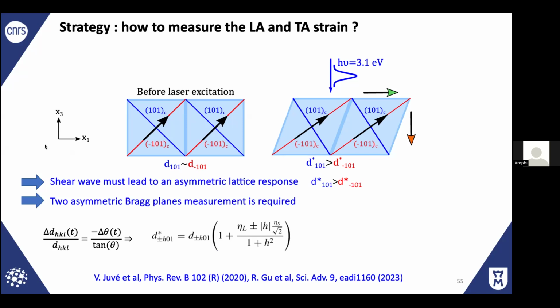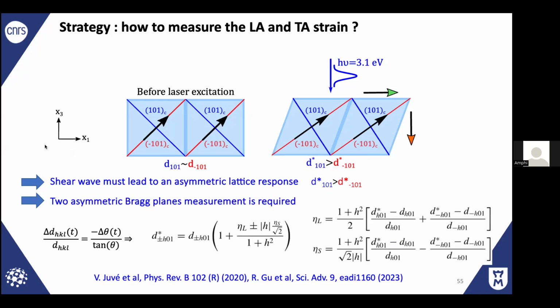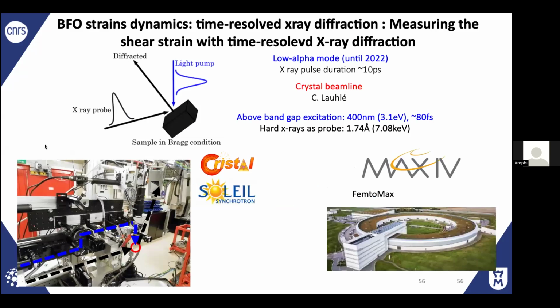If you put a tensor on that, you can immediately show that the variation of the interplanar distance is related, of course, to the longitudinal, so how the out-of-plane motion evolves as a function of time, but also to the shear. But they behave differently depending on the plane, minus 101 or 101. So if you measure two Bragg peaks and combine these two measurements, you can come back to the longitudinal and the shear strain. We did it with Claire at Soleil at that time, and recently we moved to MAX IV in Sweden, to Lund.